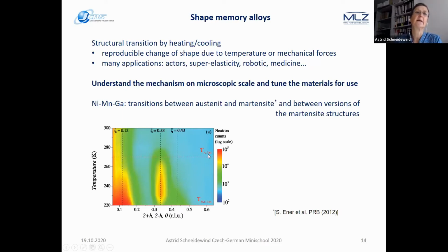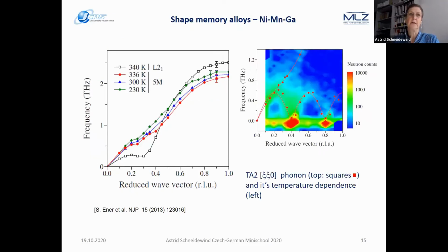And this number combined with an M is a sign that we have a modulation in this martensitic phase, which goes to coupling of the 110 planes, which leads finally to a lattice distortion. And the precursor of this distortion you can see here in the temperature dependence of the phonons of this transverse acoustic phonon, where you can see the temperature dependence here.